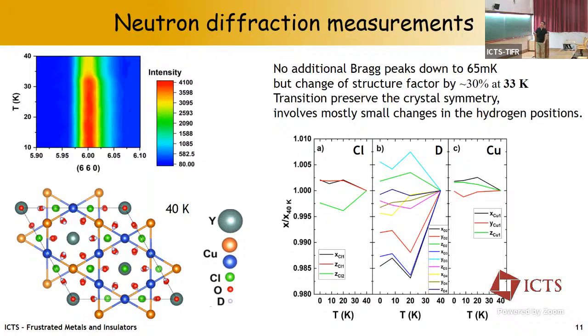Okay, what we could see is a strong change of intensity of the structure factor at 33 Kelvin. And from the refinement, this was interpreted as actually there are tiny changes in the structure, which are mainly changes in the position of the deuterium. Here the scale is really extended. It's a 2% change in the coordinates of the atoms. So if you have very good eyes, but I don't think you can see, if you look at the white dots here, which are the protons, you can see when you go to 20K, they change a little bit, and the other atoms basically stay the same. Tiny reorganization of the hydrogen atoms.